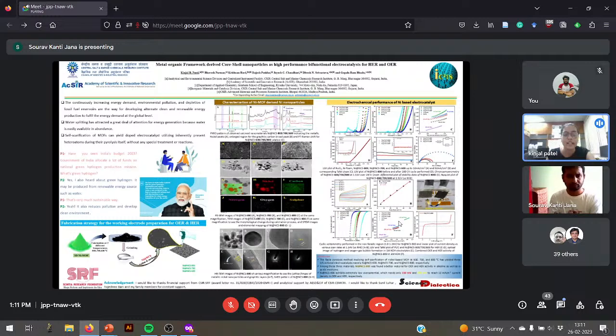The powder XRD data shows three sharp diffraction peaks, which suggest metallic nickel, while one more broad peak is also observed at 26 degrees, which is due to graphitic carbon. The Raman spectra shows three different peaks, which correspond to the D band, G band, and the 2D band. The D band is associated with defects and disorder in graphitic carbon, while the G band is associated with sp2 hybridized carbon-carbon stretching.